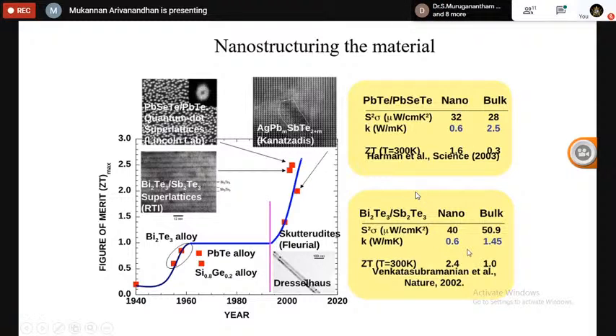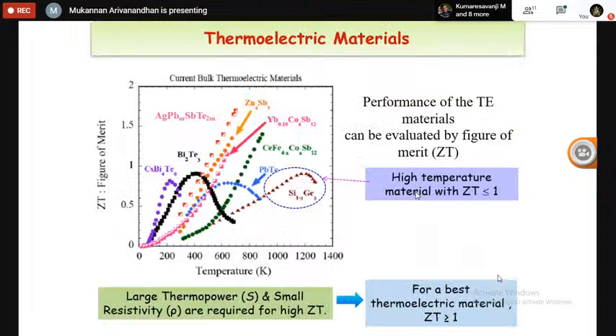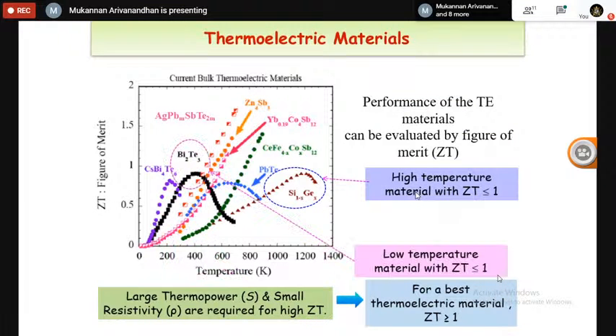Okay, so similarly for the bismuth telluride and antimony telluride nanostructures, it shows high thermoelectric performance compared to the bulk material. These are some of the examples from the literature. Most of these materials are under R&D, and some of them are commercially available, like bismuth telluride and silicon germanium. Silicon germanium is the only material, especially among semiconductor-based materials, which can withstand more than 1000 Kelvin. The rest of the materials are quite stable only below 1000 Kelvin.